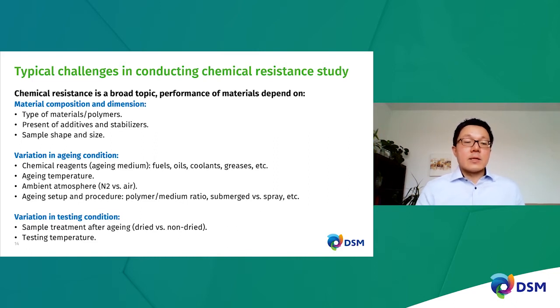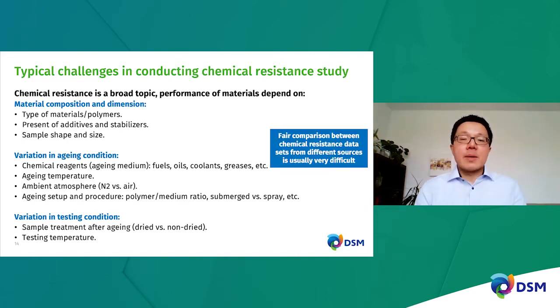The third is related to the testing conditions. So beware. If you do testing on samples after aging, sometimes the performance of the dried sample versus non-dried sample can be quite different. And also beware of comparing different results from different testing temperatures. So in essence, on fair comparisons between chemical resistance data from 2 different sources: if you have data from 2 different sources and try to compare it, be very careful, because if you do not know exactly the aging condition used to generate such data, typically this data cannot be compared directly.